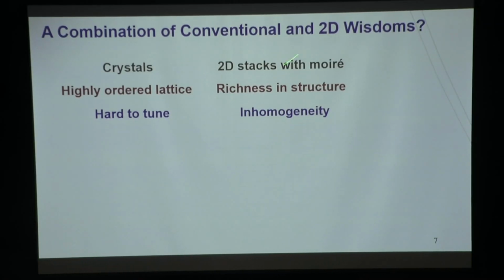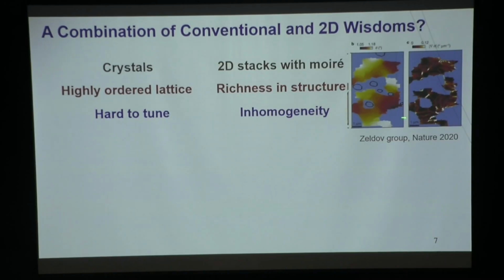On the other hand, the stacks of 2-dimensional materials, especially with Moiré, are very rich in structure. You can have unlimited combinations of these 2D crystals, and that's what they can give you. However, it suffers from a type of disorder that you don't really get from crystals. Because there's no chemical bonding between layers, strain can easily build up between the layers and distort the spatial structure that you wish to be uniform. For example, if you get two pieces of graphene and put them on top of each other close to the so-called magic angle, like my colleague Pablo did, you're going to get superconductivity. However, microscopically, there's a lot of twist angle variation due to this inhomogeneity. So you're not really getting a homogeneous superconductor. Instead, you get a percolating network of supercurrent.